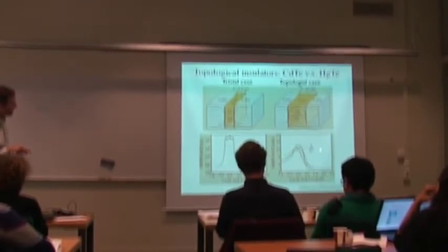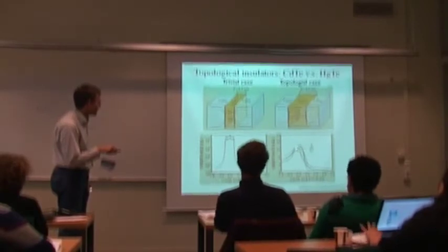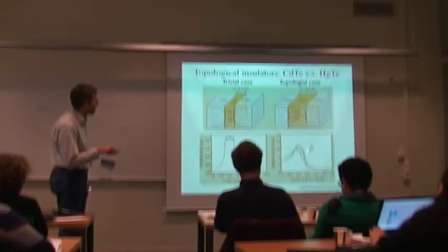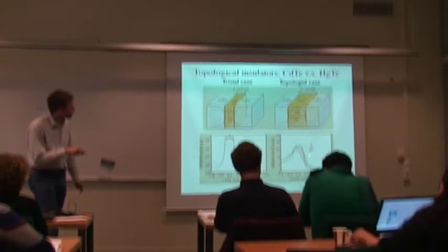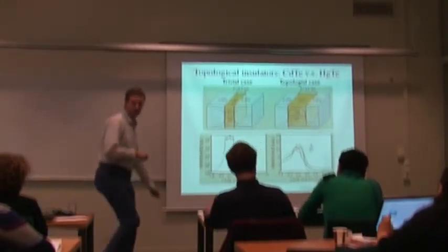Then they increase the thickness of their mercury telluride region, and there you see that. This curve is for a thin layer, and here you have various thicker layers, and there you see that the conductance is, well, not really quantized like the integer quantum Hall effect, but you see that it takes a quantized value. The conductance becomes very close to this h over 2e squared. Here they plot resistance, so it would be 2e squared over h in conductance units.